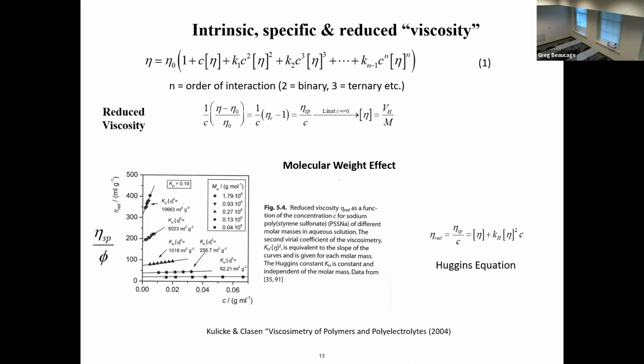So Mark-Houwink would be that the intrinsic viscosity equals K. There are two Mark-Houwink coefficients, K and a. K is a prefactor, and then the molecular weight to the a. Then a of 0.5 would be a Gaussian chain, 0.8 would be an expanded coil, 2 would be a rod, which would be like a protein, and then 0 would be a solid object if a is 0.